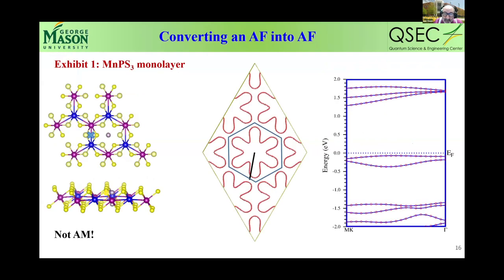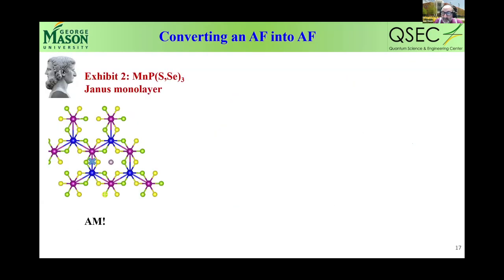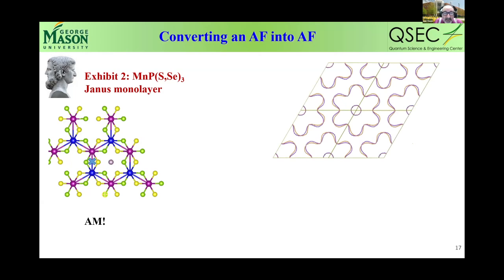You can clearly see how, remember that was my Fermi surface here, and now how this Fermi surface becomes when I introduce this Janusization. You immediately see that there are some other aspects here, very interestingly, in terms of rotational symmetry. Because you may remember that for another hexagonal material, we had by symmetry a nodal plane at kz equals 0. So you would think that it's not possible, but it actually is possible.